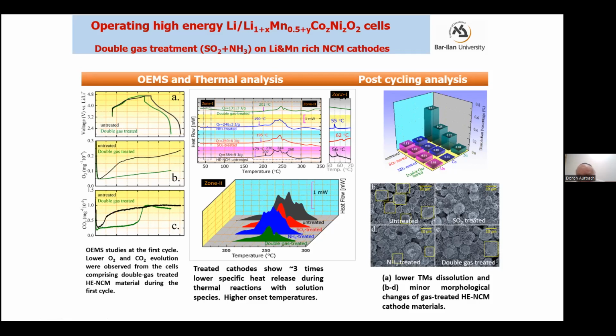And after 400 cycles, we do postmortem analysis. We look at the materials and we examine to what extent the morphology of the cathode material remains unchanged. And indeed, when we have electrochemical stabilization, the morphology is also stabilized.